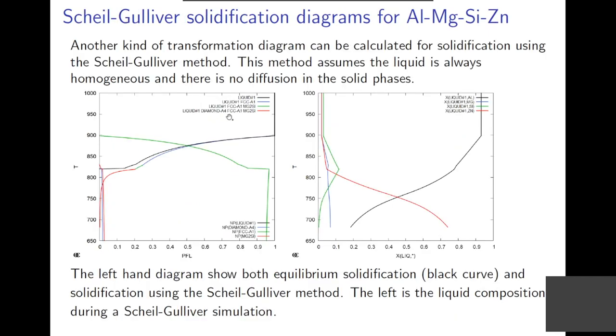And one can also do this kind of Scheil-Gulliver solidification diagram. It's a bit cryptic here, but in the stable solidification, you would have the first solid formed here, which is the aluminium phase. Then basically until here, you will have just aluminium dendrites forming, and then you will get the Mg2Si, and then the zinc will solidify. So at equilibrium, you also will be solidified at this temperature.